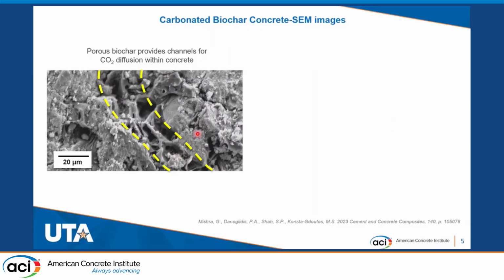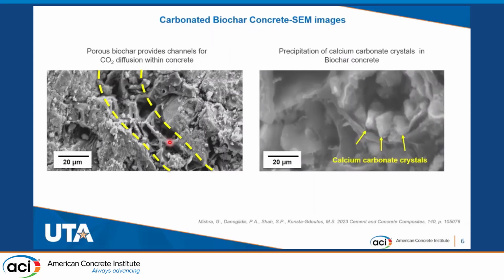Here in the SEM picture, we see a network of this porous biochar, and this creates continuous channels within the cementitious matrix and facilitates the diffusion of CO2. And these porous pathways facilitate the preferential precipitation of carbonates, as shown here in the SEM picture in the right part of this slide. We see hexagonal and cubical shaped carbonate crystals within these biochar channels, and we can say that there is precipitation of calcium carbonates within these biochar networks in the concrete matrix.